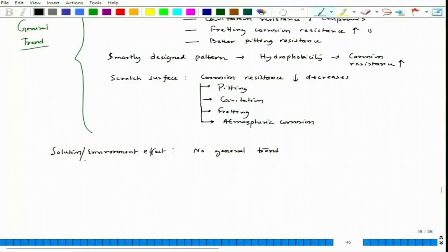Now, that means the environment and solution, or electrolyte, or corrosive medium, will be a factor, that means it can be detrimental to corrosion resistance or it can improve corrosion resistance. So, if we see overall, we see composition, grain size distribution, morphology, and surface strain. If surface strain is compressive, at times we get very good corrosion resistance. For example, in the case of reactive metals, surface strain can improve corrosion resistance. In fact, if surface strain is compressive, that means if we have shot peening, then stress corrosion resistance and even corrosion fatigue resistance improve. So, this factor also plays a role.